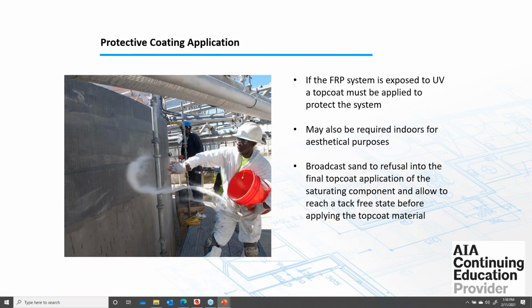Next slide. If the FRP system is exposed to UV, a top coat must be applied to protect the system. It may also be required indoors for aesthetic purposes, so the engineer will reinforce his column and the architect will want to hide it with acrylic paint or something like this, so we can hide the structural intervention. For that, the contractor has to broadcast sand to refusal into the final top coat application of the saturating component and allow it to reach a tack-free state before applying the top coat material.